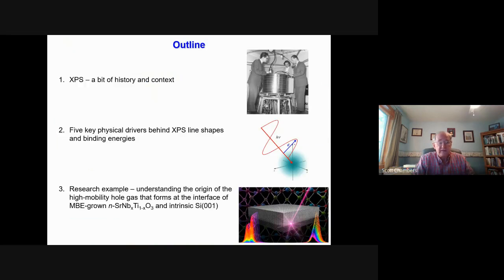Well, what I'm going to do today is I'll start off with a little bit of history behind the technique, and then I want to spend the bulk of the time talking about 5 main physical factors that determine what a line shape and a binding energy are for a given element in a given orbital. And then I'll finish with a recent research example having to do with a very unexpected result, where we found that a high mobility two-dimensional hole gas forms at the interface of niobium-doped strontium titanate and undoped silicon. Completely unexpected result that baffled us for a long time, but with XPS, we were able to figure out what it means and why it's happening.